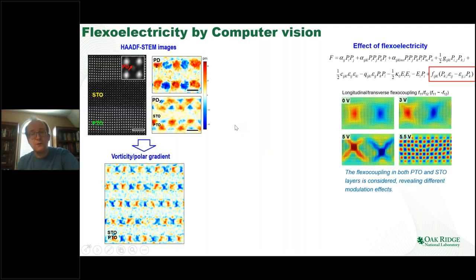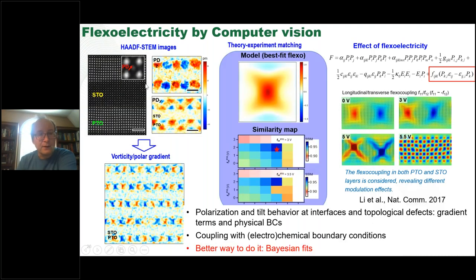This approach can be taken much further. So this is an example of the ferroelectric vortices observed by the Berkeley group. They look at the ferroelectric lead titanate, and because of the screening, lead titanate forms the vortex-like ordering of the polarization vectors. So it turns out that the shape of the vortex is strongly related to the strength of the flexoelectric coupling inside the material.